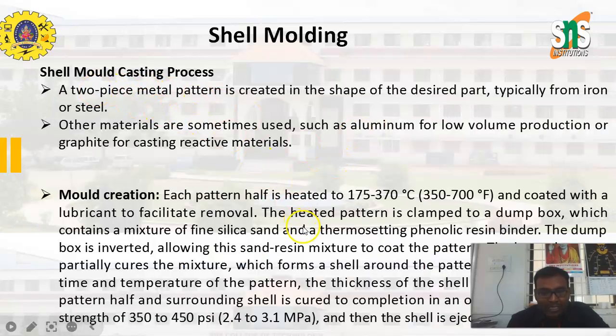We will explain in detail. The first step is that a two-piece metal pattern is created in the shape of the desired part, typically from iron or steel. Other materials such as aluminum can also be used in the process. First is the mold creation. Each pattern is heated to a certain temperature, that means 175 degrees Celsius to 370 degrees Celsius, and coated with a lubricant to facilitate the removal.